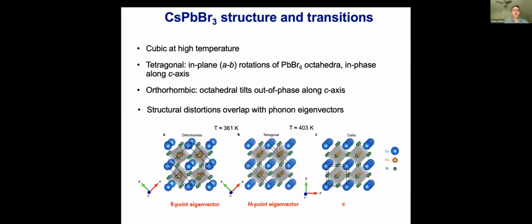And so it's a perovskite. So at high temperature, you've got the typical cubic perovskite structure. And upon cooling below 400 Kelvin, there are Glazer tilt systems, so lead bromine octahedra tilts that distort the structure into a tetragonal space group here. And then upon further cooling a few tens of Kelvin, there are further tilts superimposed, leading to an orthorhombic structure.